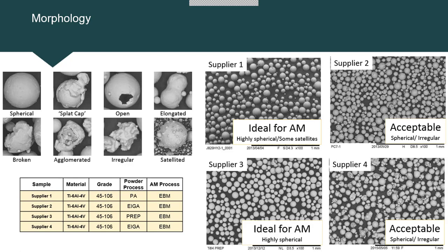So if we look at the 4 suppliers here, again, they're completely anonymized, so you can't see who they are. But generally speaking, we can start to make some assertions about which powder batches would be best. In this case, generally speaking, morphology at least, they're all quite acceptable, but some hit that level of sphericity better than others. So supplier 1 and 3 in this case, we say, well, they're really ideal. They're very highly spherical, very low satellites, very low agglomerations. Supplier 2 and 4, we can accept that morphology, but it's not as ideal.